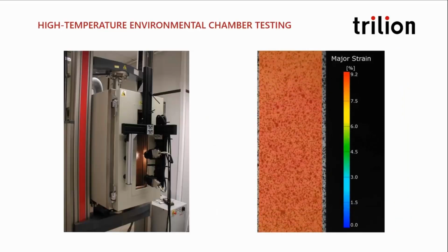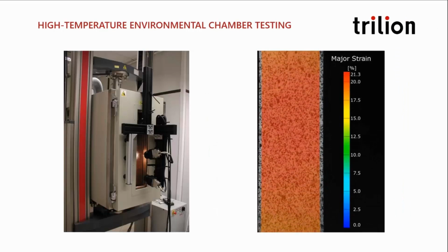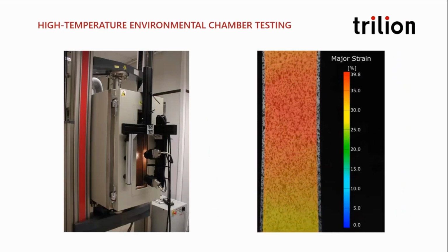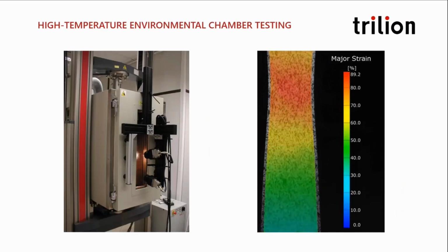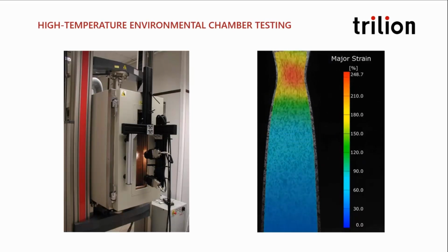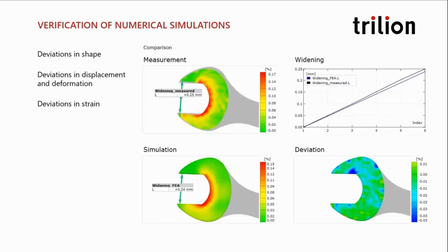The system is independent of temperature, as I mentioned before, and can see through a chamber window to make strain measurements such as this tensile test of magnesium at 300 degrees C. We can go upwards, up over 1400 C in fact, and we do account for the distortions of that glass. ARAMIS works great for comparison to simulation. It looks and feels like FEA software already, but it is full field 3D reality.